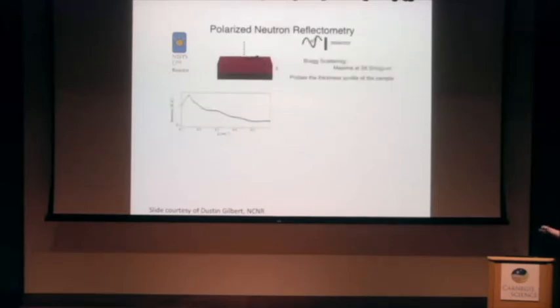And we get some profile similar to X-ray reflectometry, where this structure is due to Bragg scattering, as well as the thickness of the film and the contrast of the scattering density of the substrate with the film. And you get a sense of roughness, and you get a sense of film thickness out of the Q spacing of these wiggles, as well as how damped they are, how underdamped they are.